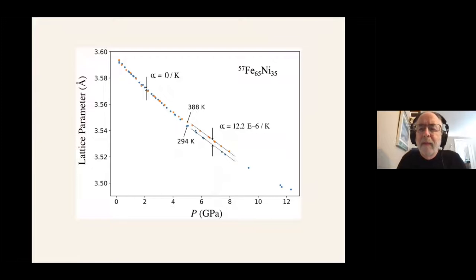Anyway, we made our own sample of Invar. It's not as big as his. It was iron 57 enriched, so we could do nuclear resonance scattering. And here's the lattice parameter versus pressure. It was done at two temperatures, so these should be the same if there's no thermal expansion. At higher pressures, though, we get a thermal expansion over 94 degrees Kelvin or so that is reasonable. It's typical of other iron nickel alloys that are not exhibiting the Invar effect. Now, the interesting region, as you see, is below about 4 gigapascals. And under pressure,